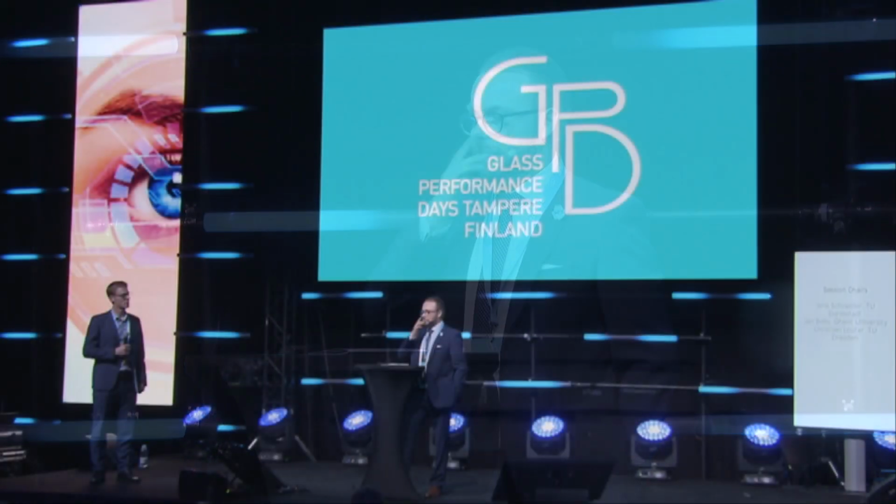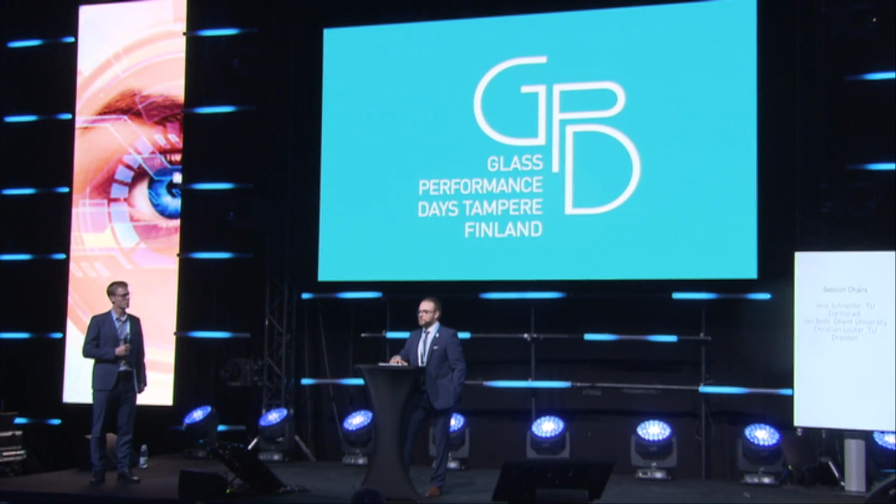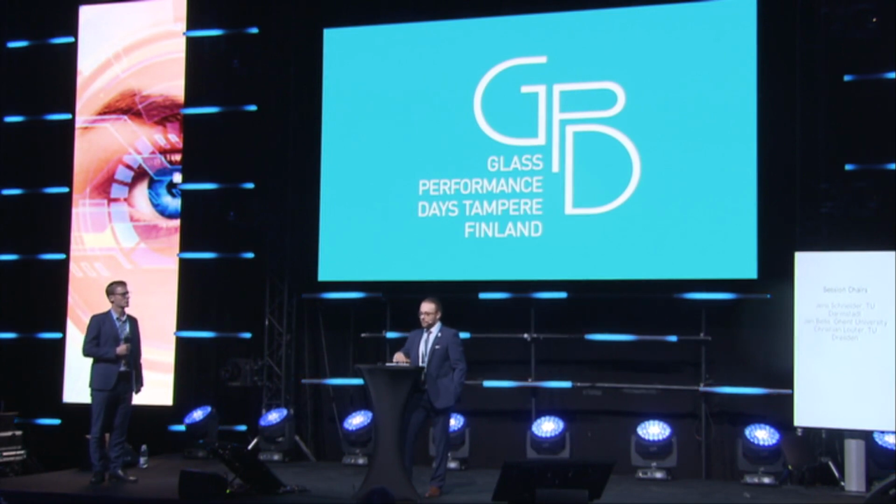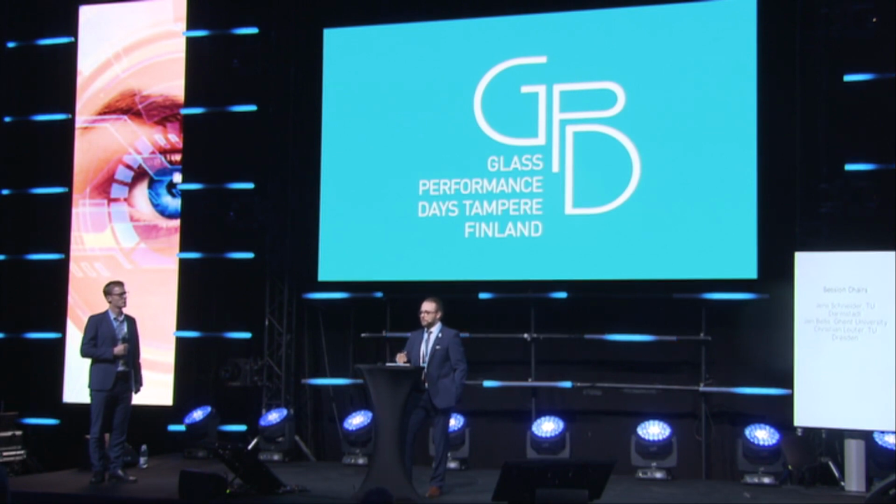this is able to solve the cavitation effect numerically. However, I used this model to approximate my experimental data, just the virgin loading, and was not able to recover the initial stiffness, the cavitation point, or the post-fracture behavior. So in my opinion, the assumptions of John Ball and Oscar Lopez-Pamies and so on started from a mathematical view, and John Ball is a mathematician, I think.